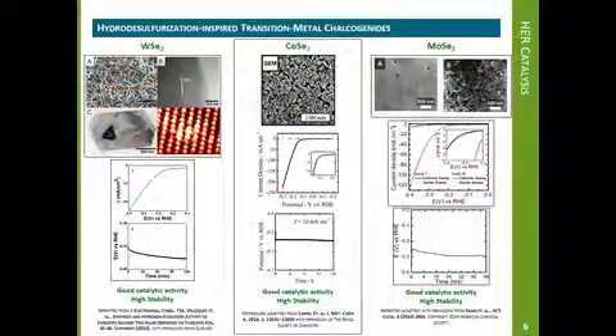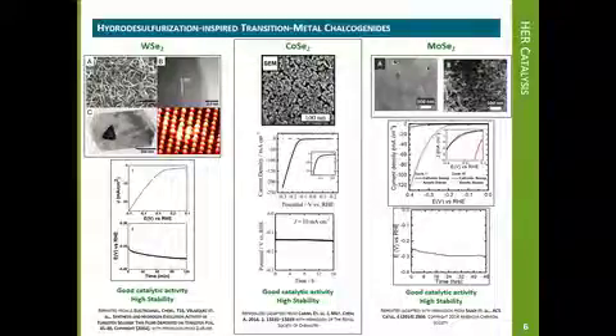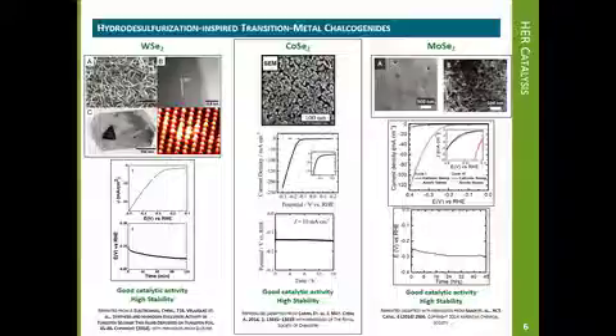One approach to the discovery of new HER catalysts is hinged on the hypothesis that HER shares similar reaction intermediates with hydrodesulfurization, or HDS, a catalytic reaction that has been vigorously investigated in the petroleum industry. Surface science studies of HDS catalysts, like molybdenum sulfide, have unveiled the catalytic role of coordinatively unsaturated edge sites on these layered materials. From a family of related metal chalcogenides, JCAP has produced HER catalysts that are both active and stable in 1 molar sulfuric acid. A quick inspection of the voltammograms for different metal selenides reveals an improvement in overpotentials, from 350 millivolts for tungsten selenide to 140 millivolts for cobalt selenide, needed to deliver the required current density of 10 milliamps per square centimeter.